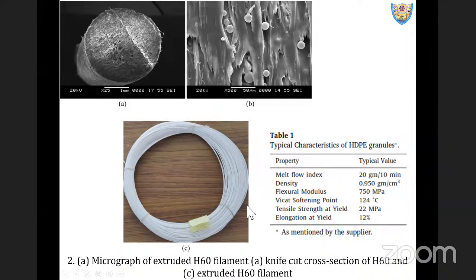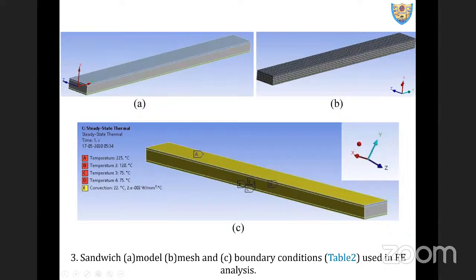Then we went ahead with the sandwich manufacturing. As all of us know, sandwich composites are manufactured in a two-step process. First, the core is manufactured, and then the skins are wet by an appropriate resin placed below. Then the solidified core is placed on the top, and then the top skin is again placed onto it. The mold is closed for 24 hours or based on the curing temperature, and then we get a solidified sandwich.